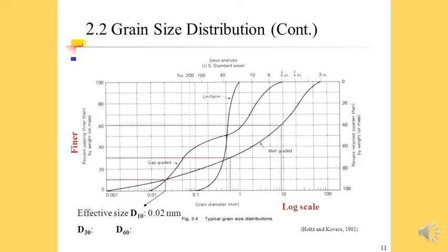With the gap graded, we can see how you've got that sort of step, that wave pattern in it. And so you can see that there's a lot of aggregate which is around the 5 millimeter diameter size, or anywhere between 1 to 10 millimeters. And then there's also a lot of aggregate between 0.1 to 0.01 millimeter diameter. So in this case we really have some big stones mixed with silt.